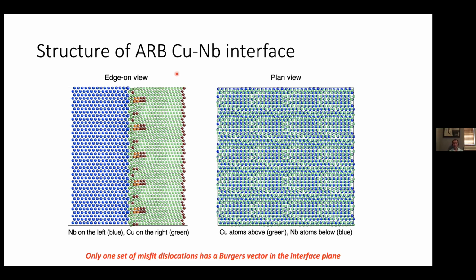The models that we use here are, for example, for copper and niobium. Copper is an FCC material that is extremely well represented using EAM, embedded atom, potentials. Niobium is a BCC material that is adequately represented using EAM potentials, although not as well as copper. Copper niobium, the binary system, has very limited solid solubility. Copper and niobium are like water and oil. They don't mix, they tend to phase separate. They don't form compounds, they don't form intermetallic phases. So constructing a potential that reproduces that kind of simple phase diagram is not too difficult, and you can easily show that your potential reproduces it.